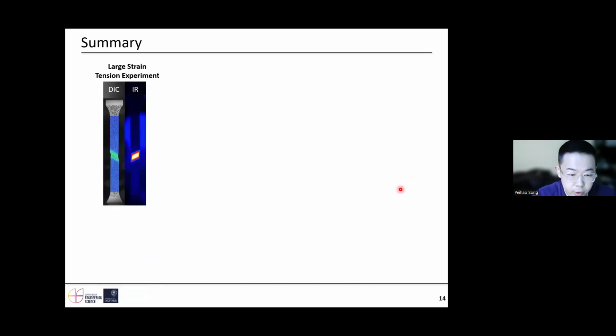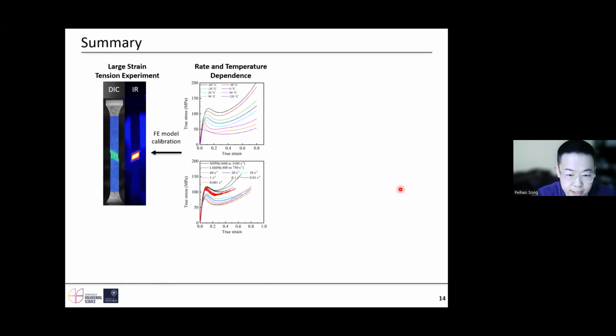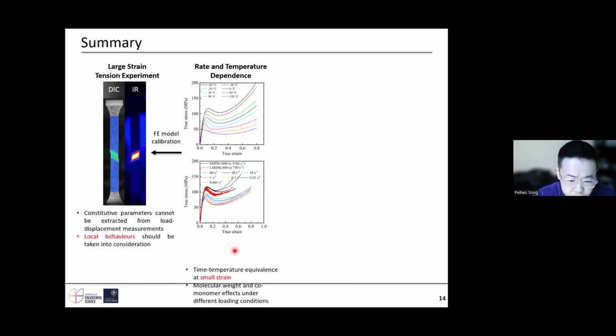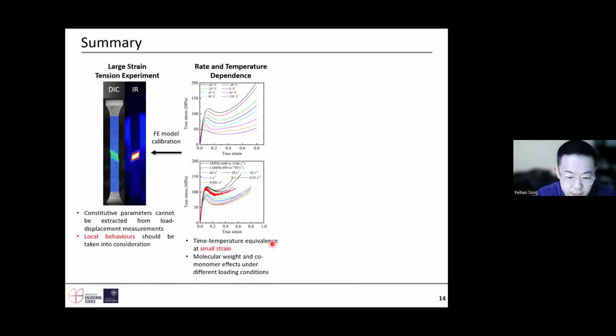It brings me to the summary of my research. My research started by doing large strain tensile tests using digital image correlation and infrared techniques. I used rate and temperature dependent compression tests to understand the experimental observations during the tensile test. The consequence is that we cannot only use the global behavior to examine the constitutive parameters; we should think about the local behavior, such as the local true strain versus time curve. And through this study, I validated the temperature and time dependence at very small strain and understood the molecular weight and comonomer effects during different loading conditions.